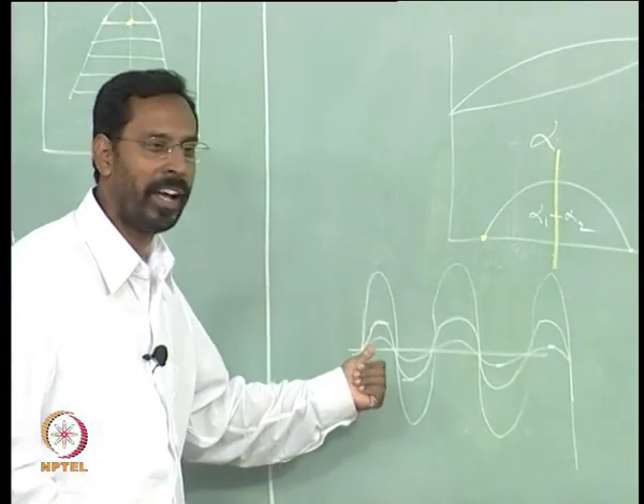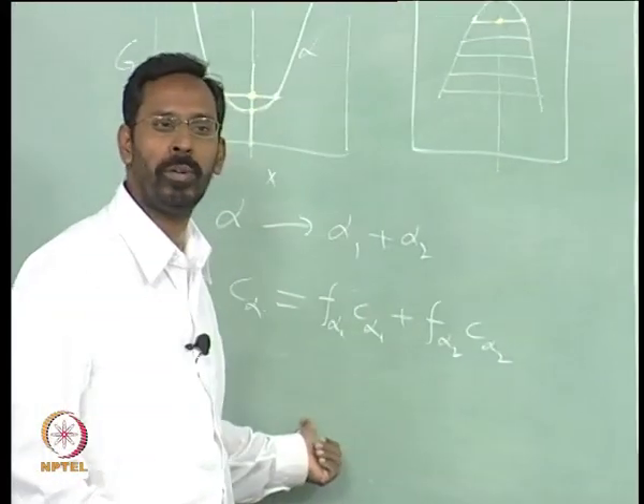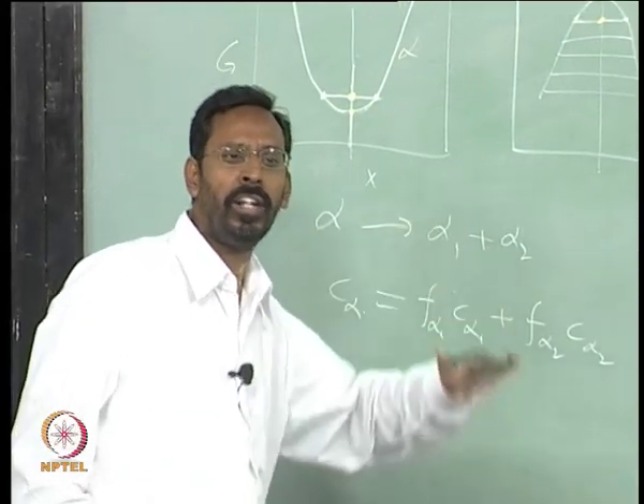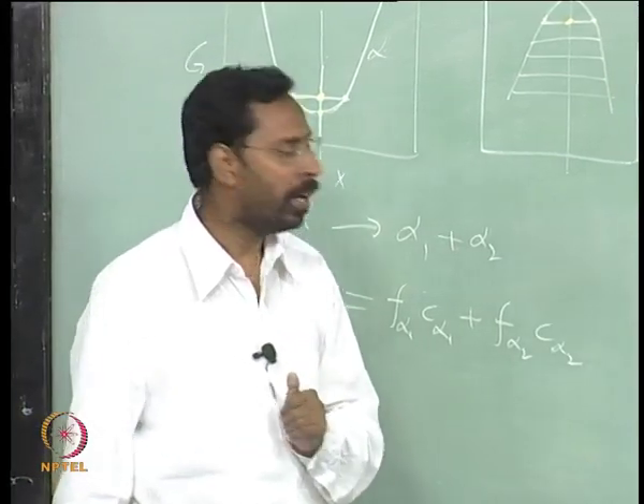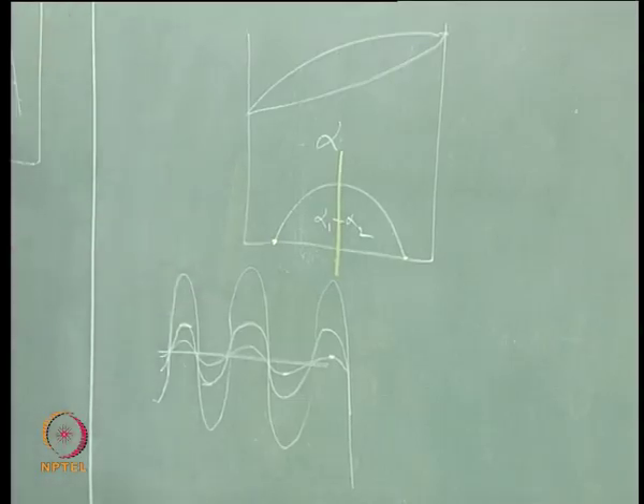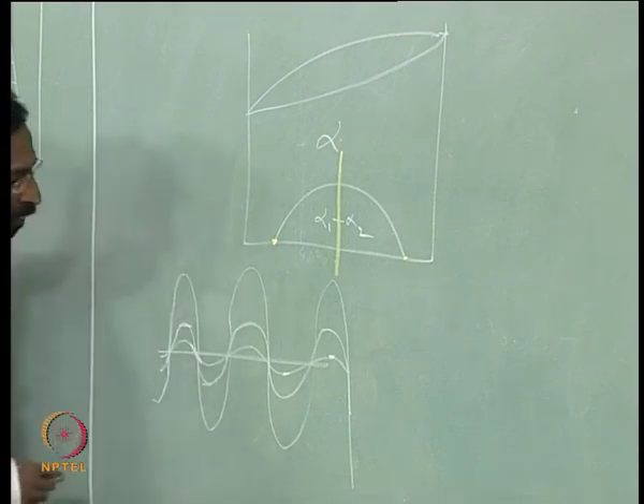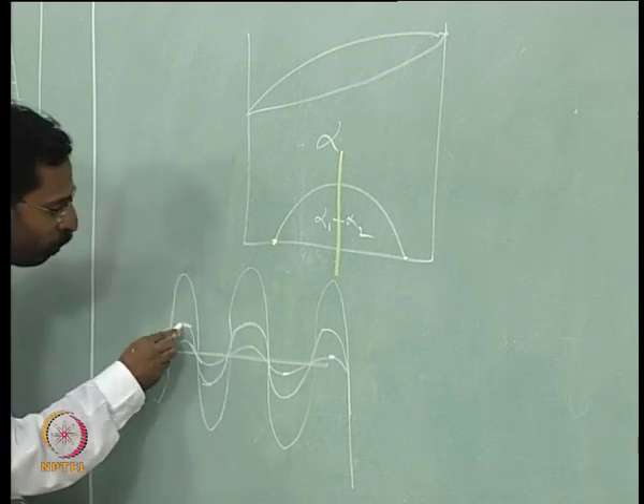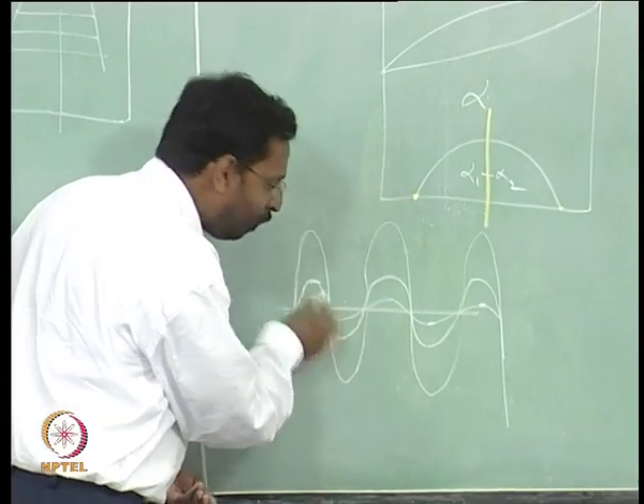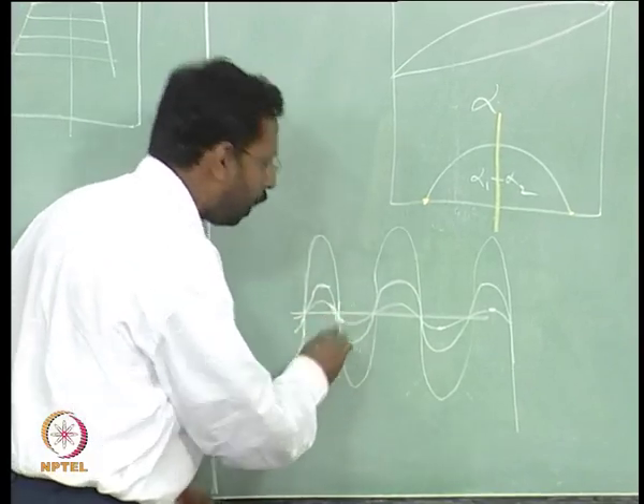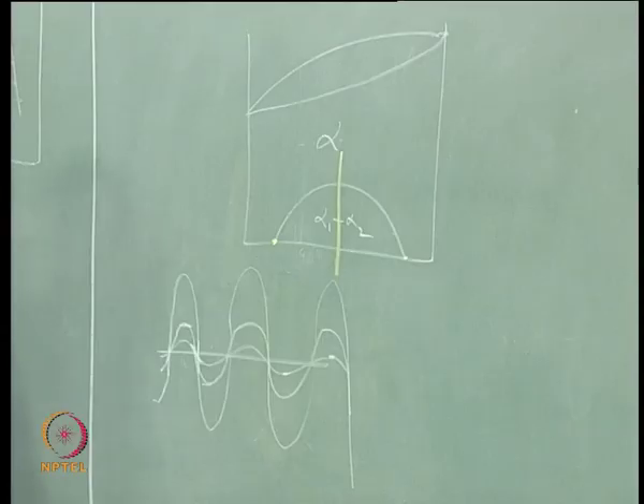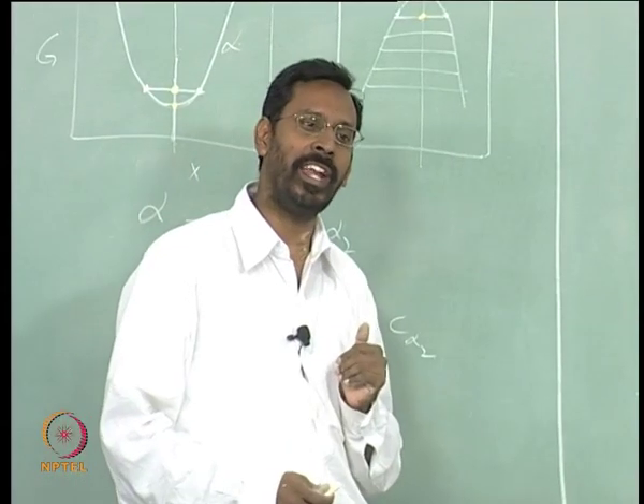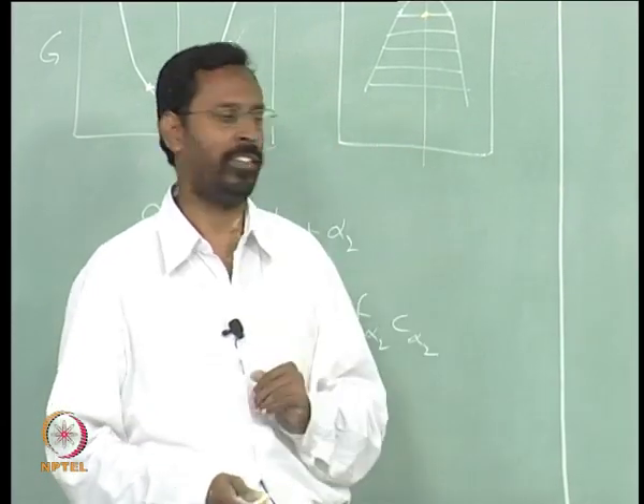and this is in contrast to what I have shown you in precipitation, where the gradient will keep on decreasing as a function of time. Here the gradient is actually increasing as a function of time. If you look at the interface, if you want to call this one phase, this another phase, at the interface the gradient keeps on increasing, whereas in normal precipitation, at the interface between the theta phase and the alpha, if you draw a gradient, that gradient will slowly decrease, because if you remember,